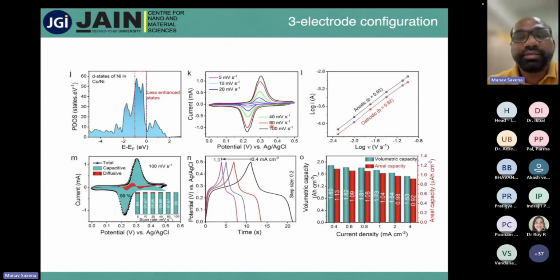So we found this theoretical study helpful, and then we have done the CV at different scan rates, and we found that the b value is close to 1, which shows a capacitive type of storage. However, we can see the material shows a CV with a redox peak, which is contradictory.